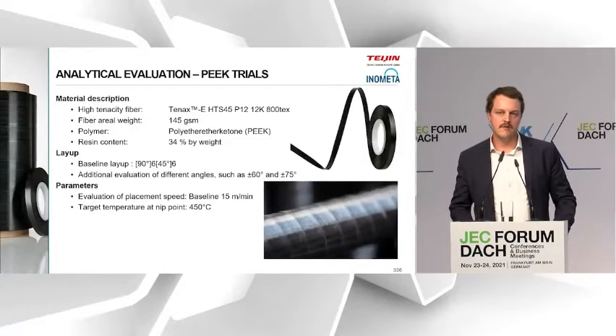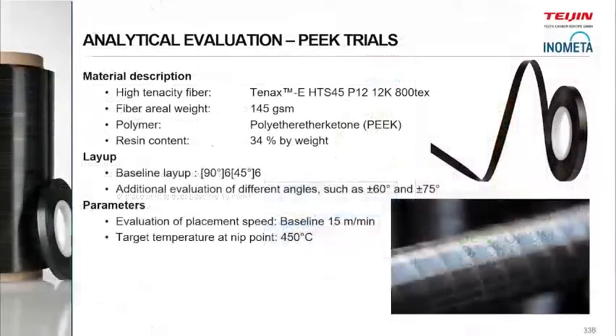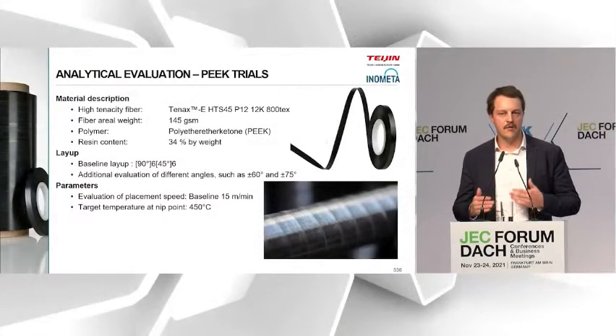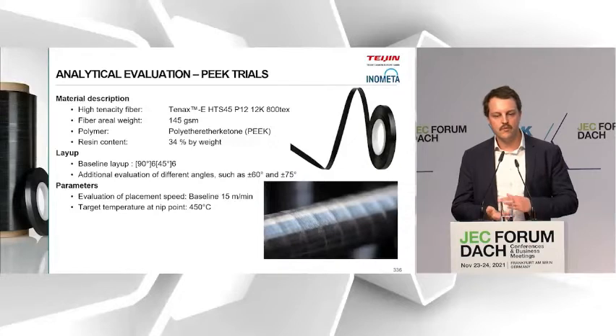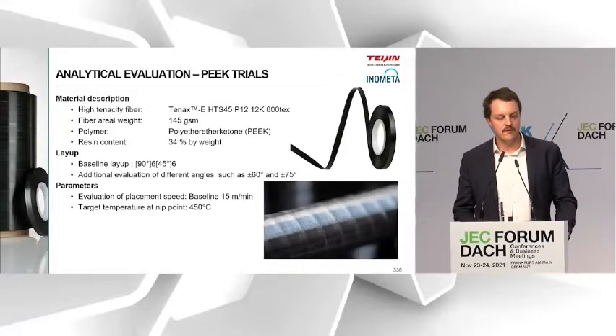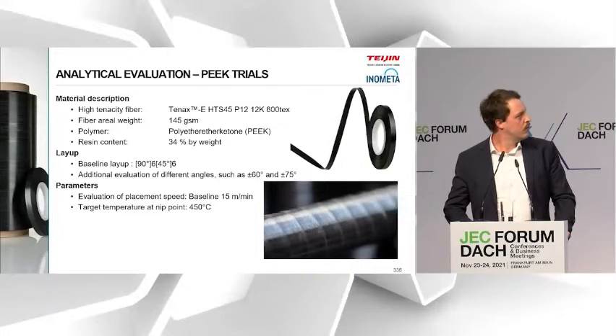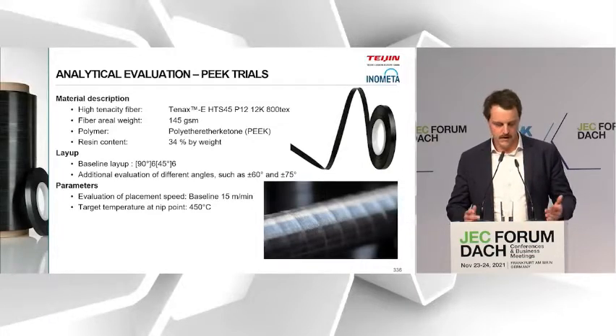The baseline part, the wound part, always uses the same layup. So it's 12 layers. First 90-degree layers, and then plus minus 45 around. But nevertheless, we also performed additional tries to see the effect if we change the winding angles, how it affects the gaps or voids between different layers. So that's all taken into account, and the trials are still running on that focus. The first baseline was 15 meters per minute where we started. And on the next slide, I would like to show you when we do microscopic evaluation as a quick first insight to see how the consolidation quality is.